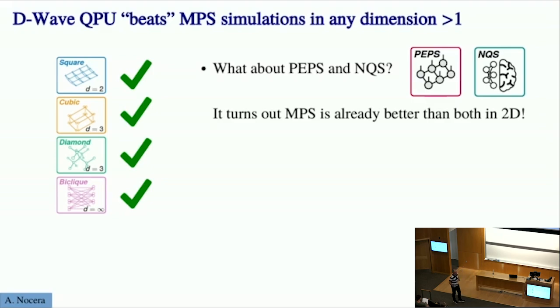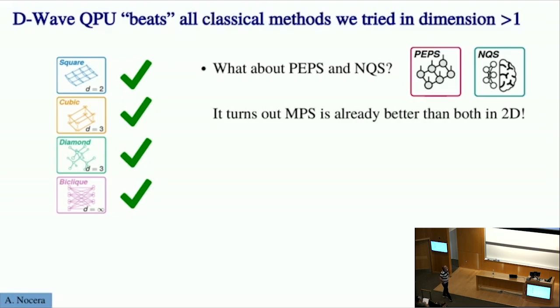Because, as I said before, in terms of the entanglement, the problem of PEPS, for instance, is not just the bond dimension, but the size of the neighborhood. There is a contraction complexity that is exponential in PEPS to compute expectation values. So you need to truncate to some tensor neighborhood update that you need to do to compute expectation values. And the Kibble-Zurek physics tells you that this correlation length increases with annealing time. So if you go to times long enough, you need to increase the size of the neighborhood, and that puts PEPS, for instance, into trouble. So basically, all the classical methods we tried failed.